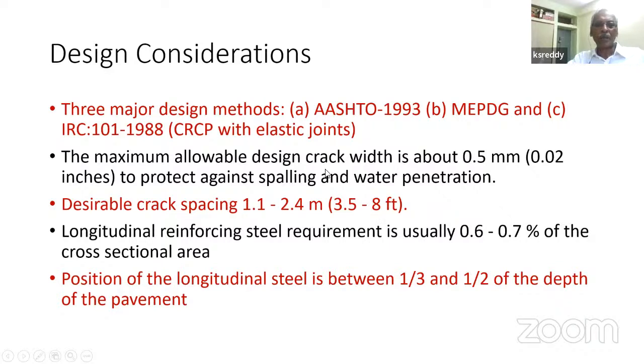These are that the maximum allowable design crack width, the crack should not open beyond 0.5 millimeter. So your design should be done in such a way that the crack width should never be greater than 0.5 millimeter. Very difficult to control, but they try and then provide some design equations and analysis for that. So that there is no spalling happening. You don't want any hard material to go into these cracks and then break the edges of the joints. You don't want water to be penetrating through these cracks. So keep the joint opening to a maximum of 0.5 millimeter.